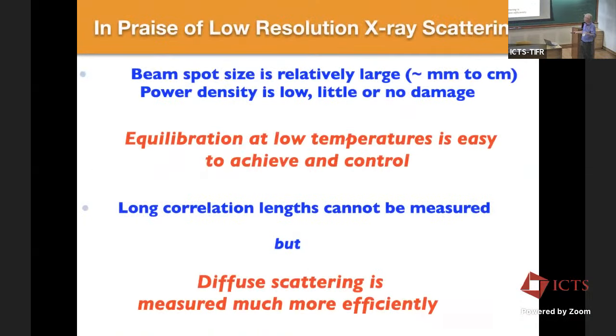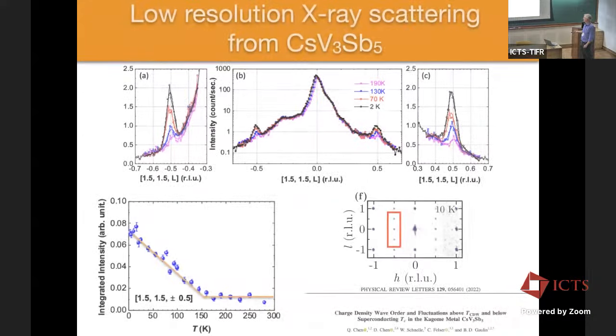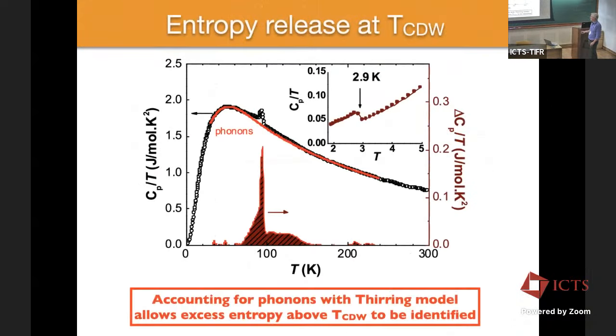So, but I am going to show you something that does show these fluctuation effects. That's what I'm going to show you next. Right, so this is the heat capacity measured over a very broad range of temperature. I've already shown you the heat capacity at very low temperatures, which shows the superconducting anomaly nicely. So this is actually C over T, so the integral of this would be the entropy associated with the sample. I mean, most of this is due to the lattice, it's due to phonons.